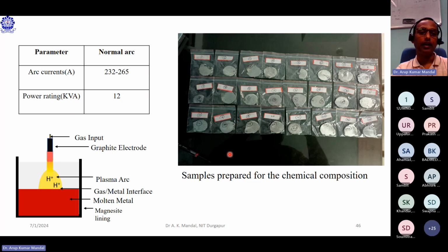Okay, and the furnace was operated at a constant arc current of 232 to 265 amperes, and 12 kVA power rating we maintain as per the arc stability from the previous experiment. We have fixed it. Then this input gas, you can see this electrode is directly exposed. It means that when the hydrogen gas is in front of the arcing zone, it will dissociate and form the plasma, and it will directly expose to the top surface of the liquid metal.